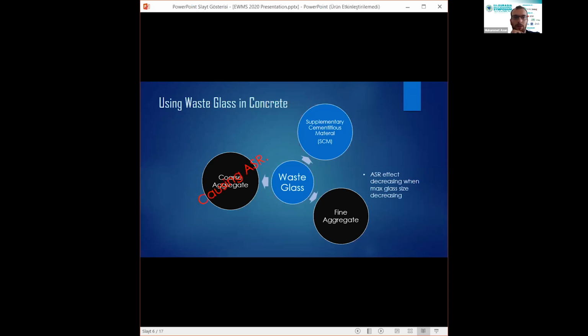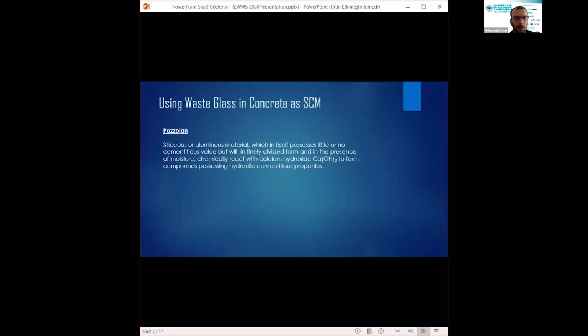Usually, partial use of waste glass instead of sand contributes to alkali silica reaction expansion, but alkali silica reaction expansion decreases as the content and maximum grain size of the glass decrease. But the subject of this study is using waste glass as supplementary cementitious material. At this point, it's necessary to define a term, pozzolan, because if we want to use waste glass as a supplementary cementitious material, it should cause a pozzolanic reaction.